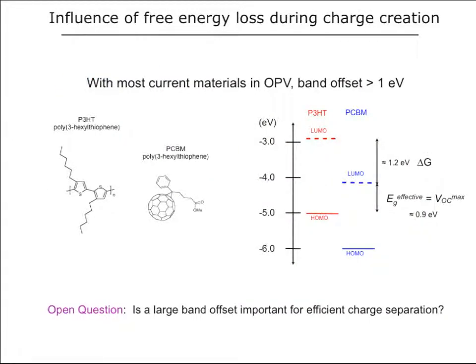Okay, a little bit more about the voltage loss. And this gets into the thermodynamic part of the talk. So when we look at the relative band structure of a typical set of materials, typical is poly-3-hexylthiophene and PCBM, we have the HOMO and the LUMO of the polymer, HOMO and LUMO of acceptor. We have this quantity, the band offset. And this is now the thermodynamic loss in the charge transfer event, delta G. In a typical device, this is an enormous quantity. This is well over 1 electron volt. So when we do that charge transfer process, we're losing all this energy to heat. What's left is the effective band gap, the difference between HOMO of donor, LUMO of acceptor. This is now the maximum voltage we can get out of the device.